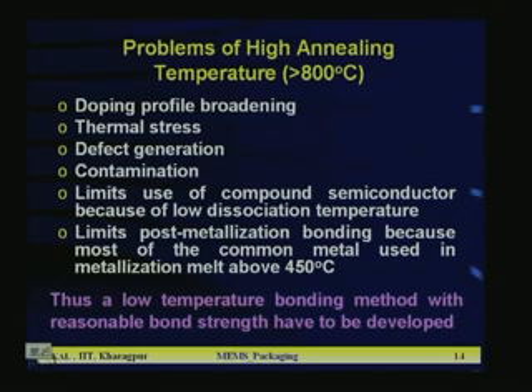Second one is the thermal stress. Obviously when you go for high temperature, then coming to room temperature, the stress development will be higher, and you require a special kind of thermal cycle from high temperature to low temperature. Otherwise a lot of stress will be developed. Then defect generation, at high temperature there is a possibility of generation of crystallographic defects. Contamination, because at very high temperature many of the impurities are mobile in nature, and a lot of contamination may disturb or may destroy the quality of the devices.